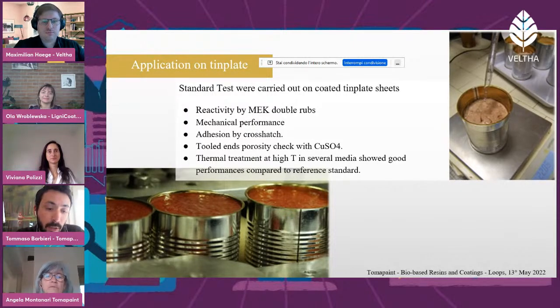Some formulations were developed and applied on tin plate sheets. Main properties were tested: chemical and mechanical resistance, adhesion, and porosity. And the results of the analysis carry out good performances compared to the reference standard.